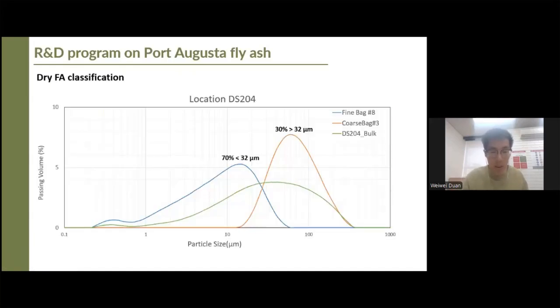Okay, that is the result of the classification. When we wash the fly ash, we try to separate the coarse and the fine fractions. And there will be 70% of the fly ash that is very fine, lower than 32 micrometer, and the remaining is greater than 32 micrometer.